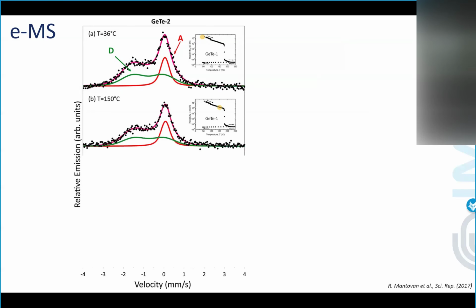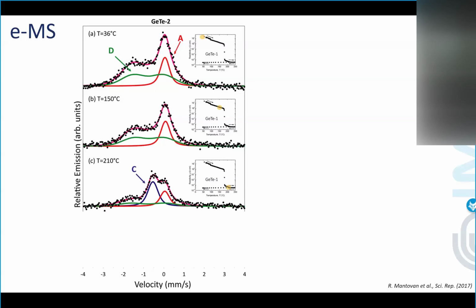And then we get close to the transition, but still before the transition, and nothing happens. But here, boom, across the transition, we see clearly the emergence of a new component. And all this was done in 10 minutes, 10 minutes, and 10 minutes. So the whole experiment is less than an hour. And so it was clearly connected to the macroscopic transition that we know exists.